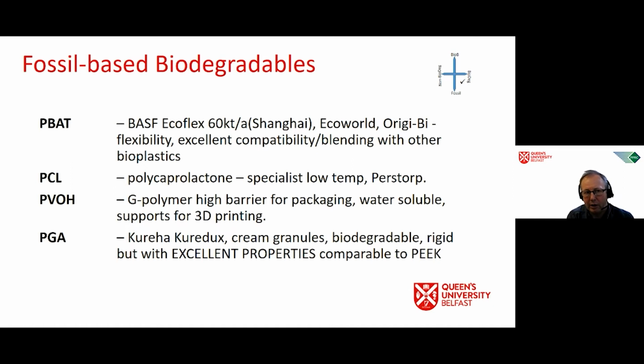Another very interesting fossil-based material is PGA, which is polyglycolic acid, and Kuredux, which is produced by a company called Kureha. This material is another rising star. It is a fossil-based biomaterial, but it has excellent flexural and tensile strengths, as well as wear properties. Historically it was used for medical sutures, but now with industrial scale production, it is expected to be able to compete with the likes of PEEK in injection molding parts. So you're talking about a biodegradable material which has the strength and wear resistance similar to PEEK, so this is expected to be a rising star in the future.